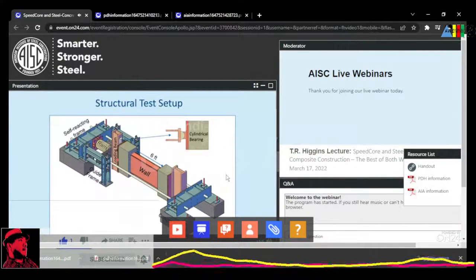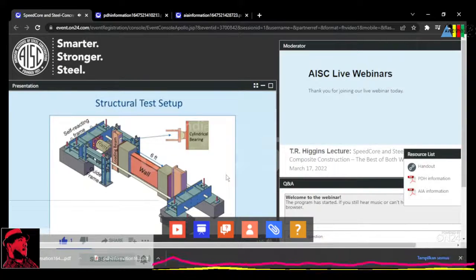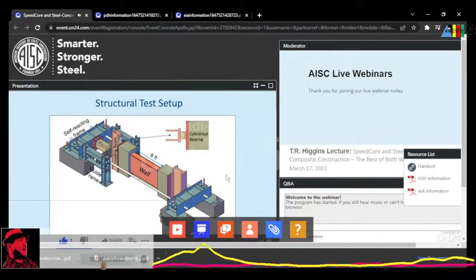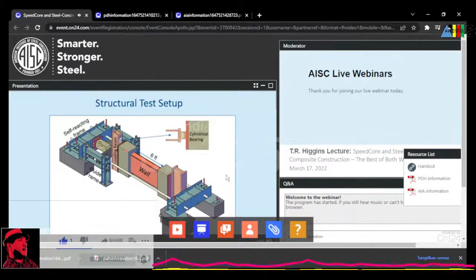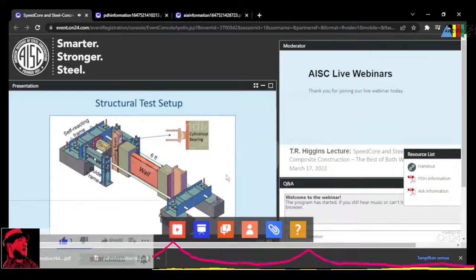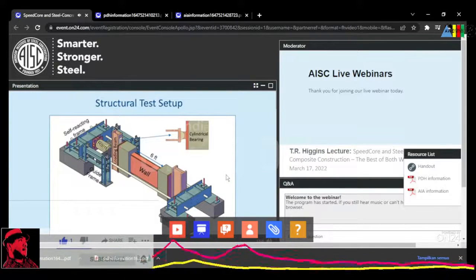We used a self-reacting structural test setup, similar to the column setup used in the past. The ends of the wall specimens were cast in reinforced concrete blocks at the ends. Axial loading was applied using a hydraulic ram, and cylindrical bearings were used at the ends to achieve pin end conditions.